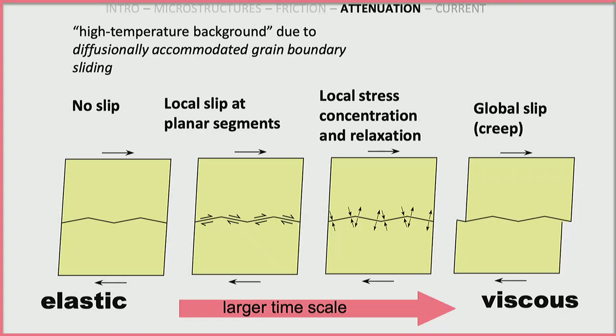What's that? If you imagine all these grains in a sample and you start to shear or deform it, the grains want to move relative to each other. The first step, it's just elastic bonds that stretch. And then the grains have to start moving relative to one another. They get caught up on each other and start to build little stress concentrations, which the system wants to relieve by diffusion at the grain boundaries. So in the anelastic regime, where it's seismic to tidal, that keeps happening over and over again, things moving back and forth in a non-permanent way.